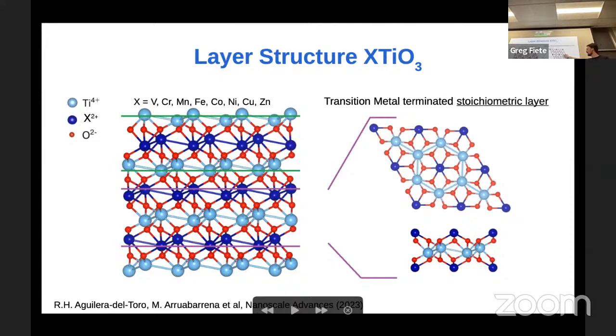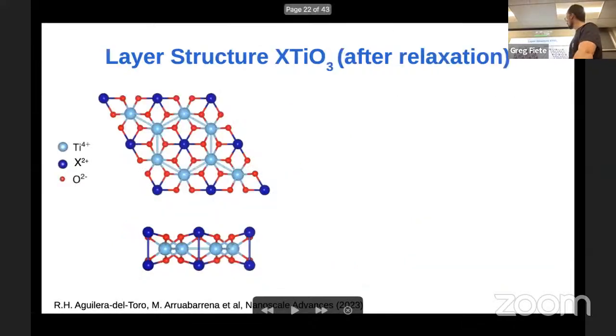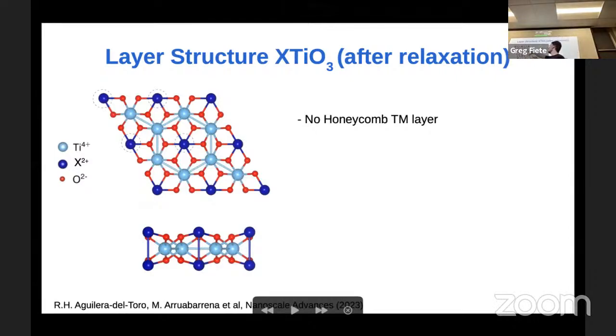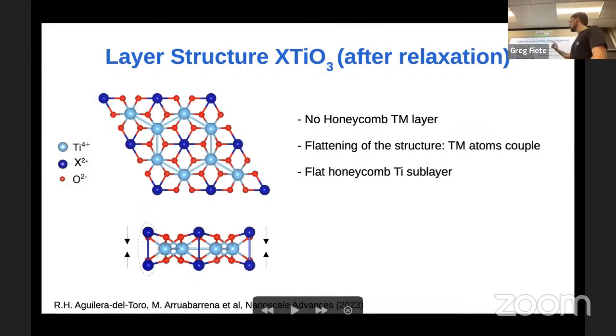It's the one that looks like this. And here you have the side view. Some things about this structure: first, we no longer have this honeycomb transition metal layer. We have lost one of the first neighbors there. So now it's more like a triangular lattice. What more? There's also a heavy flattening of the structure. It shrinks in the Z direction, causing the titanium layer to now be flat and honeycomb-like.